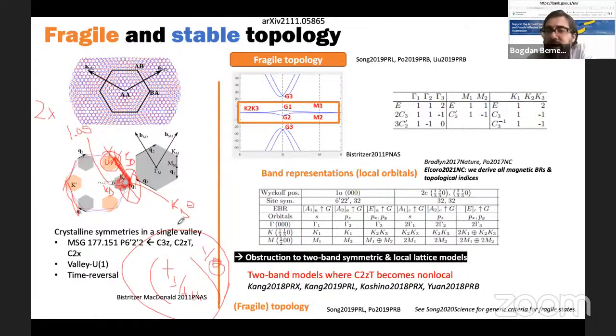So now I have a valley symmetry. And this valley symmetry in twisted bilayer graphene allows me to look at the single particle model just in one valley, the one coupling the K point of the lower layer and the K point of the upper layer by interlayer coupling. And this has an emergent symmetry in the sense that if the original symmetry of graphene involved time reversal, this emergent symmetry model of the Moiré lattice doesn't have time reversal.